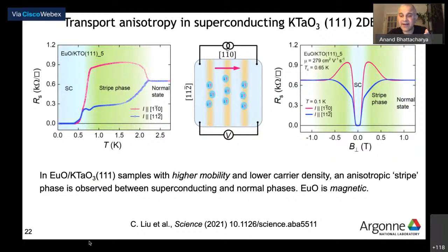So then, your logical conclusion would be that there are puddles or grains of superconductivity. They couple very strongly in one direction, but not in the other as much. We have lots of evidence for this now, but I'm going to stick to just what's in the paper for now: that this nematicity is arising out of some superconducting state.